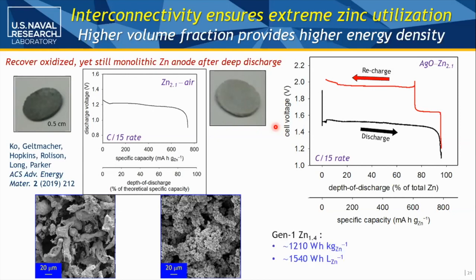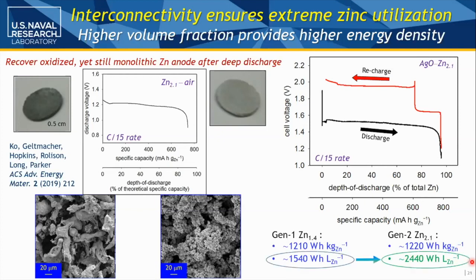So that first generation of sponge, you've got 1.2 kilowatt hours per kilogram of zinc, 1.5 kilowatt hours per liter of zinc. And as you might expect, if you go to a per gram normalization with the higher dense sponge, it comes pretty much to the same number, but where you win out is your per liter. And although I know we're used to thinking of specific capacities, and worried about weight, for most applications, it really is the energy density you want. So just that reformulated sponge has kicked it into a new phase space.